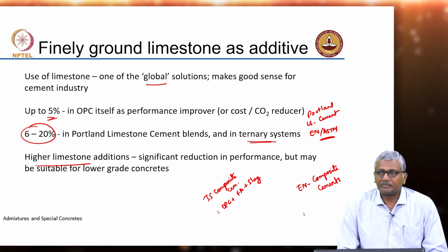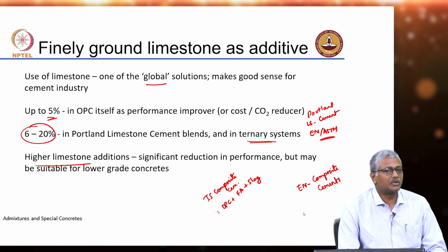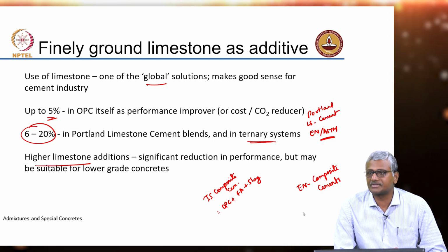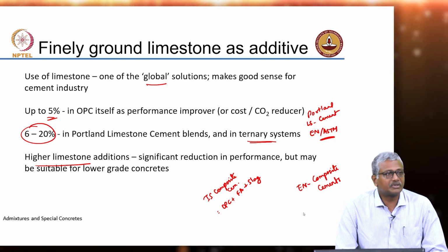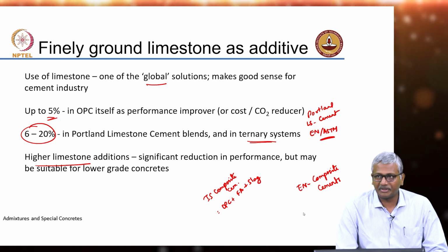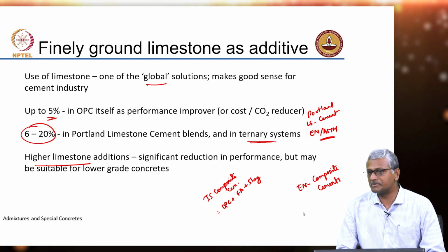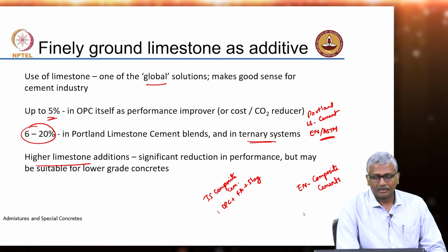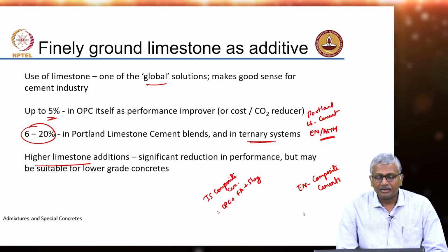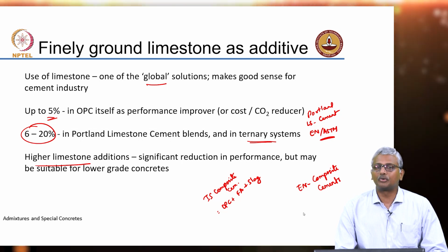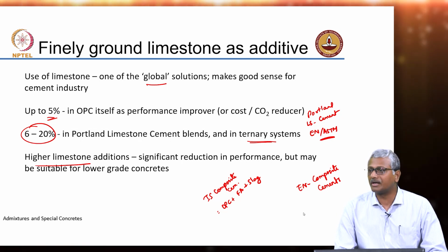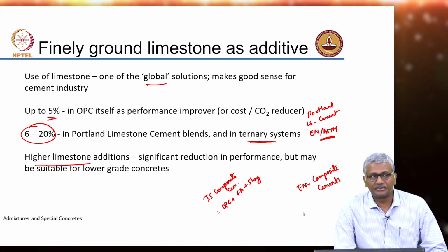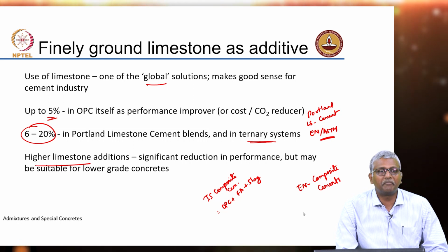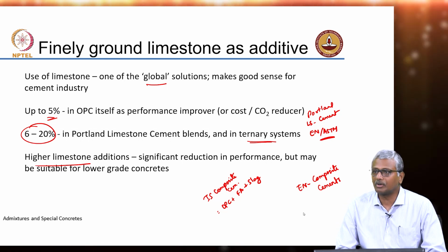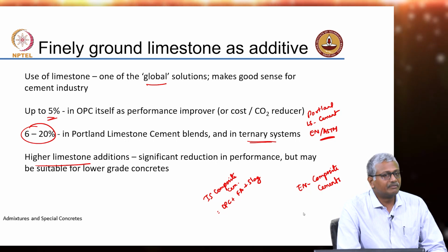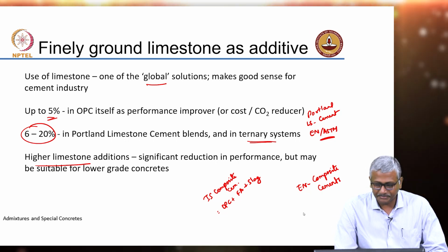But what we are primarily interested in is what will happen when we start introducing more limestone in the system, because that leads to a major advantage with respect to cutting down the overall CO2 potential of the cement. So 6 to 20% is what is permissible in Portland limestone blends that are available in EN and ASTM. But even beyond that, if we have an opportunity to go for more limestone in lower grade concrete, we should look at that option, because there is definitely some impact that can have on the concrete choices for low grades, let's say M20, M25, where we don't have to rely on too much cement being used.